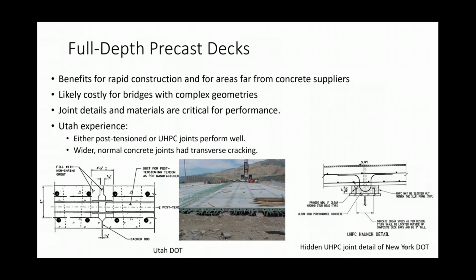It had a curve, so likely a costly alternative if you have geometry, but if you don't, then it seems to be a pretty good alternative. And for this, again, joint details and materials are critical. So Utah told us that, again, either they post-tension the decks together or they use UHPC. So that's equivalent to each other. So either of those joints perform well. In the past, they had the much wider joints with normal concrete, and those had the cracking between the panels. So the joints didn't perform very well for those.